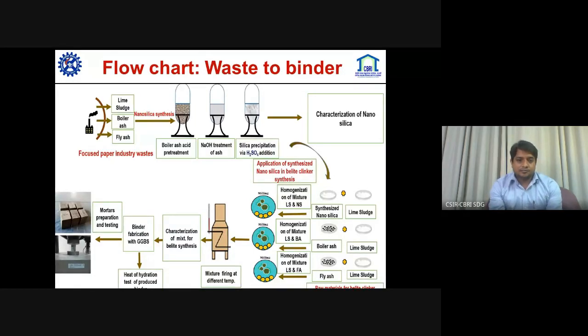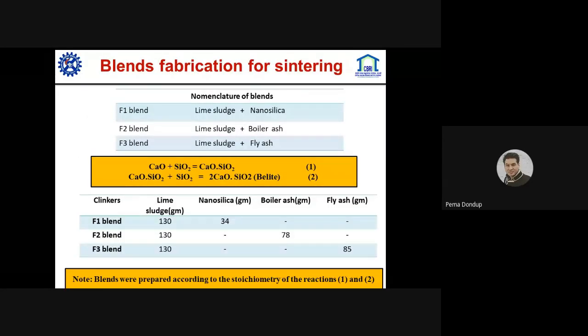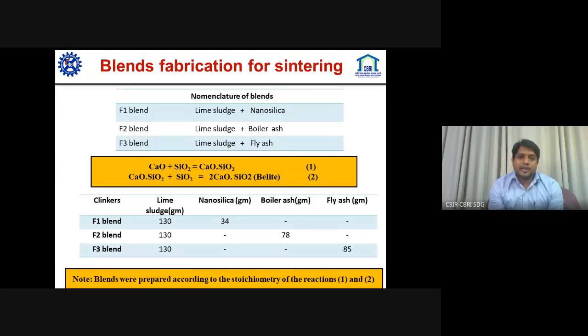from this clinker, the binder was fabricated with the addition of GGBS and tested for different properties. So as depicted in the flow chart, there were three blends: lime sludge plus nanosilica, lime sludge plus boiler ash, lime sludge plus fly ash. So basically the Belite is synthesized with calcium oxide and silicon oxide reaction.